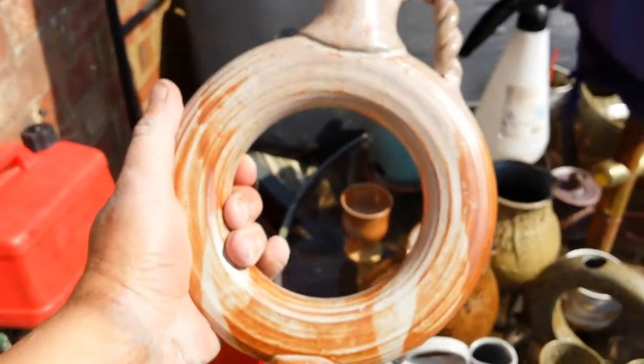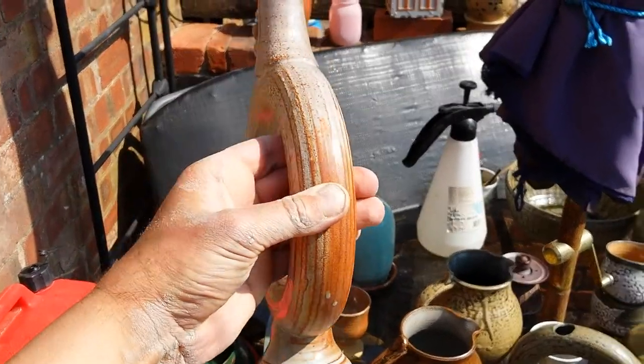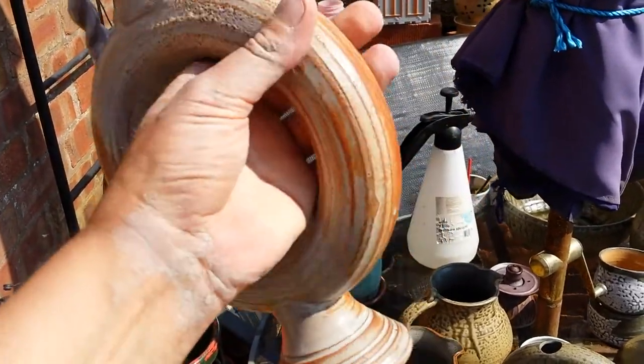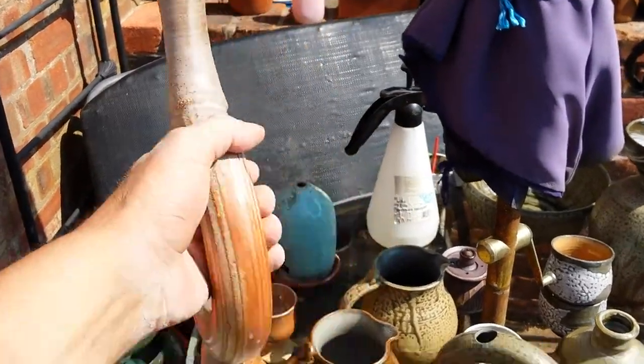My Shino — I'm much happier with it. I added some rutile to the glaze, which may be why I'm getting the nice rusty colour, or it may be because I fired for an extra half an hour in reduction.